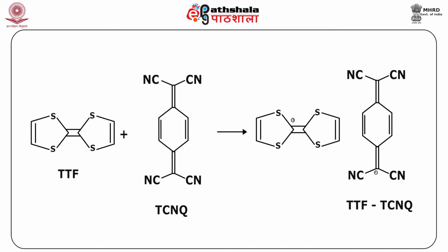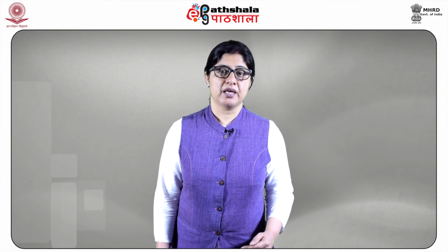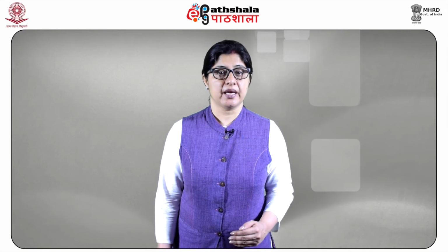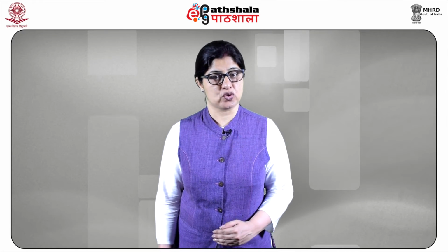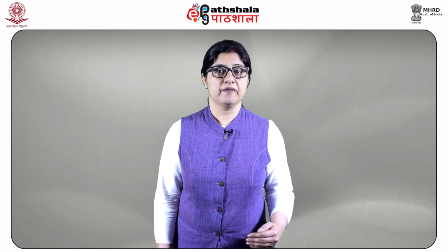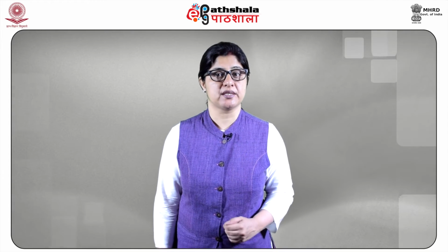Later, another work was done on TTF-TCNQ, where conductivity reached about 8000 ohm⁻¹ cm⁻¹ at about 59 Kelvin, but below this, conductivity fell to a very low value. The organic compounds conduct electricity when either extra electrons are present or a vacancy of an electron exists.